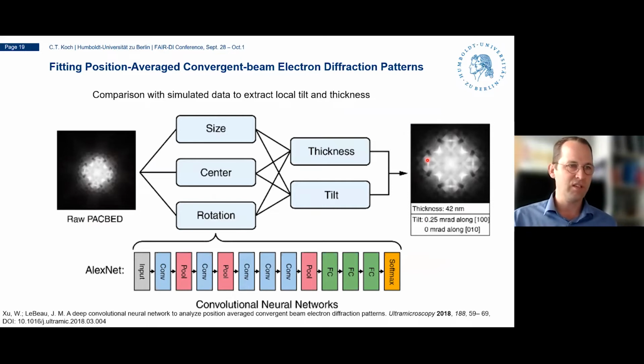And it has been shown that these patterns are very sensitive to the thickness, for example, and you can then extract very precisely the specimen thickness, which you need to know for further analysis of your data. So again, this neural network needs data. It needs input from many different crystal structures and could then be shared online with others.